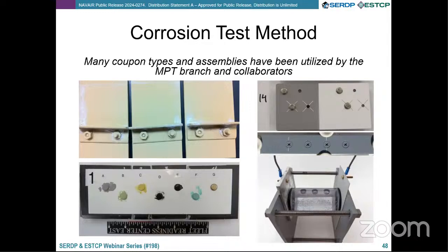And finally, we didn't just develop a coating itself, but we, as the Navy, developed a series of test methods by which we wanted to make sure we were evaluating the films in the correct way. And there's lots of different specs and standards out there for evaluating coatings in a galvanic manner. But we wanted to make sure of two things. We wanted to make sure that the performance of the coating could easily be replicated in chambers as well as outdoors, and was also later validated on aircraft to have the right representation of coating performance when comparing one to another. But also, as I'll explain in a later slide, we need a coating galvanic coupon test to be performed in the chambers that is easy to do, that is cheap and effective, and can be added into a specification.